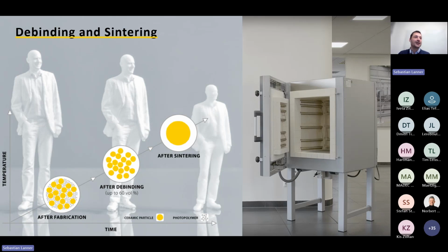In the beginning, we start with a step called debinding. With up to 450 degrees centigrade in this step, the polymer is burned out and the temperature burns out all the residual carbon in the part. The part after this stage is very porous and therefore very fragile. Here we need a sintering step. This is the second step. In this step, we go up to, depending on the material for sure, up to 1700 degrees centigrade and densify the ceramics and create the outstanding properties you might already know from ceramics. You also see on the right-hand side how such a sintering furnace could look like. And this was about the manufacturing process.